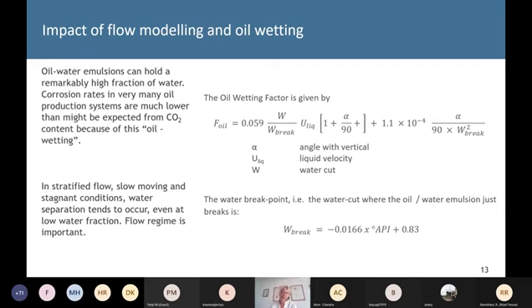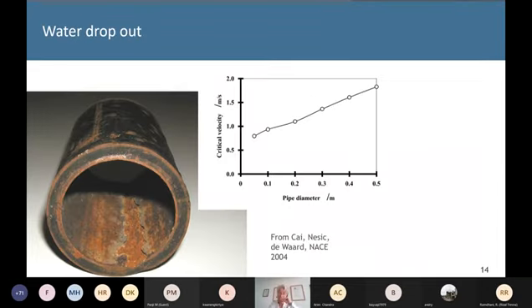So we have an oil wetting factor, which is determined from this equation, and we have within that a water break element, which is related to the API gravity. Now this part of the factors affecting corrosion was determined from real field studies actually carried out by myself and other workers in our business at a certain point in time. It was published data, and it's been picked up by many of the public models, but not all of them. And we think this is one of the key factors that helps to explain why we get certain behavior in the oil business.